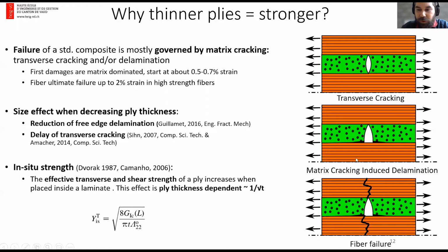In regular composites, what we have is after transverse cracking, we have generally matrix cracking induced delamination, and then at a certain point fiber failure. The use of reduced ply thickness has been shown to reduce the onset of free-edge transverse cracking and delamination. And this effect has been described very clearly by the work of Dvorak and Camanho in 2006,